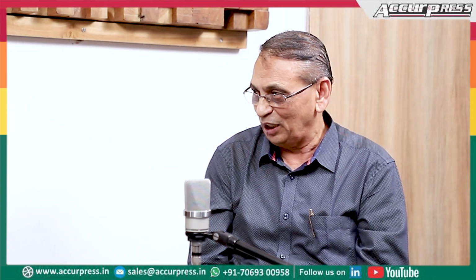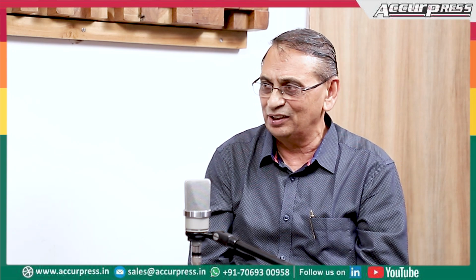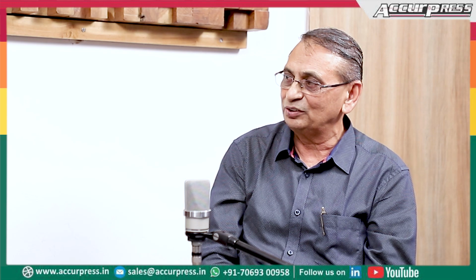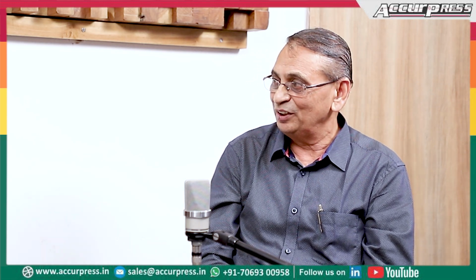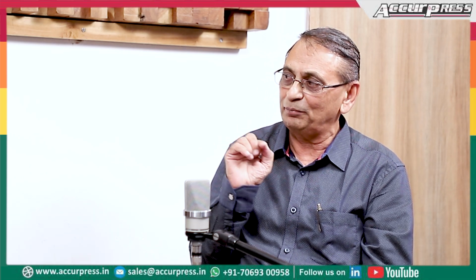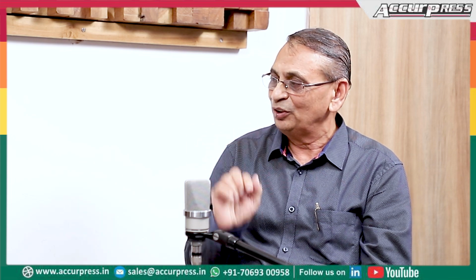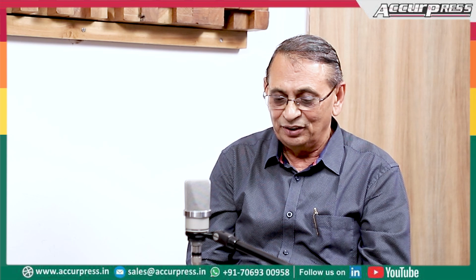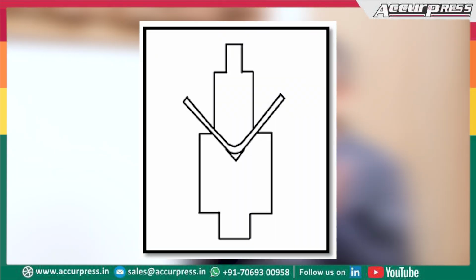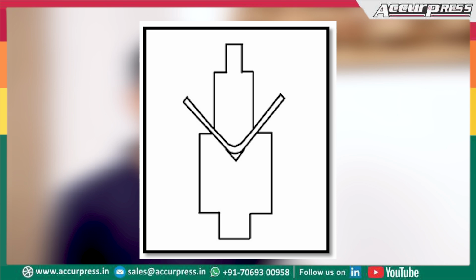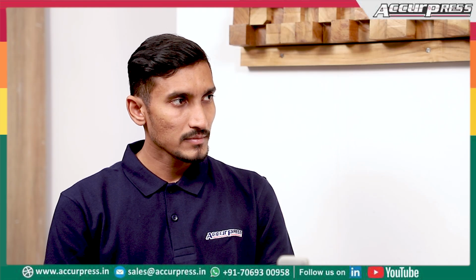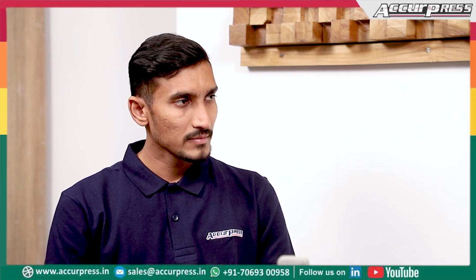The second bending type is known as bottoming. Now, bottoming is unlike air bending. A bottoming operation is a combination of both the punch radius and the die opening. These two are critical, and the punch radius must be kept as the desired radius of the job. So these three things are critical. Now the die opening should be selected such that it gives the natural radius that you have taken for the job. And springback also should be calculated before you start the bottoming operation, because in the die opening itself you should give it such a shape that when the load comes, the springback is automatically calculated in that.